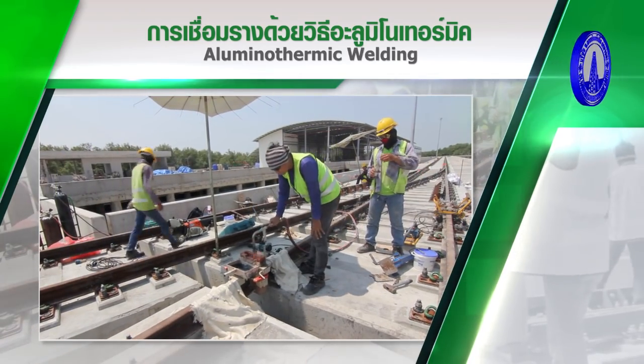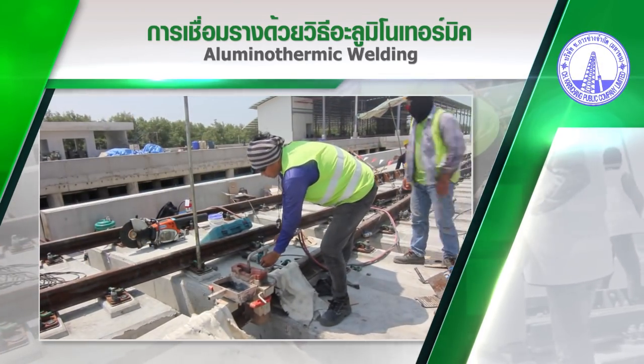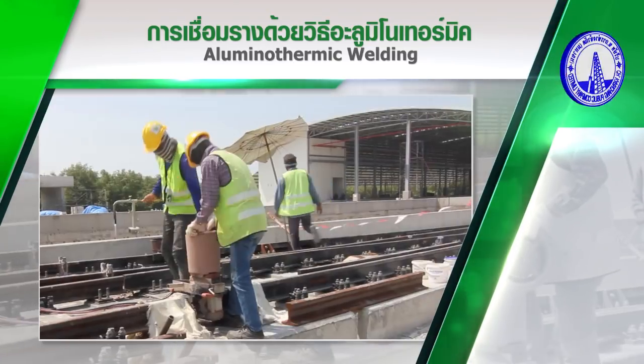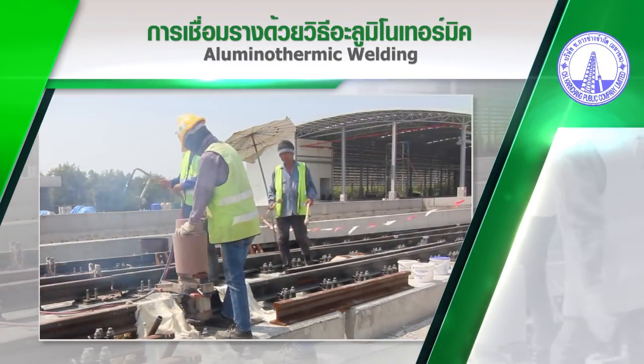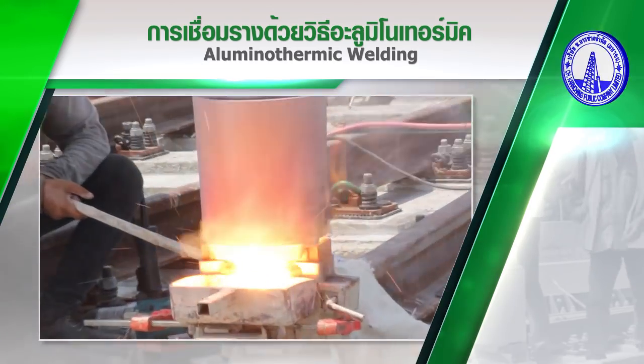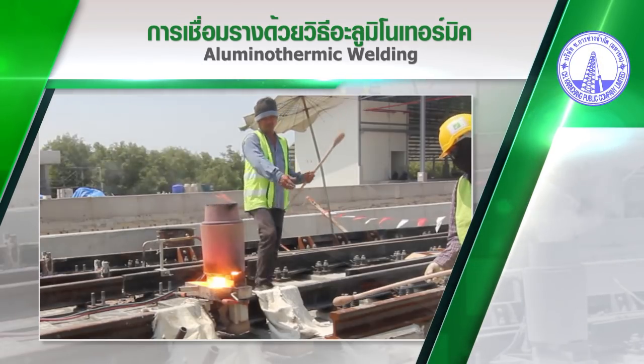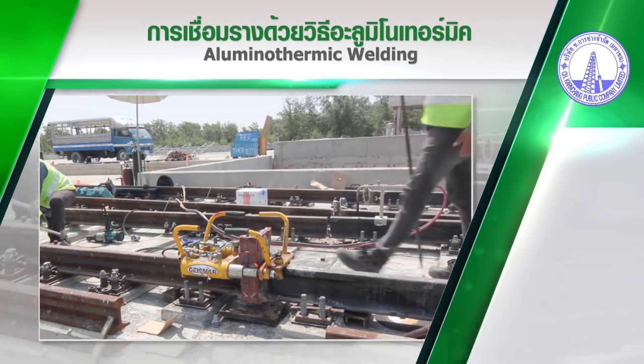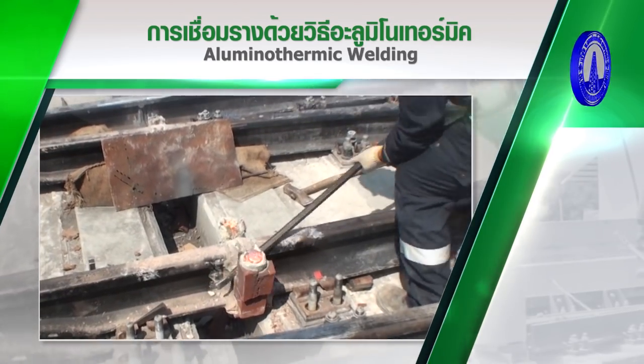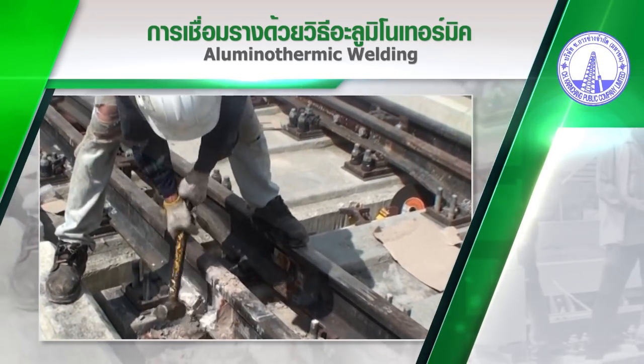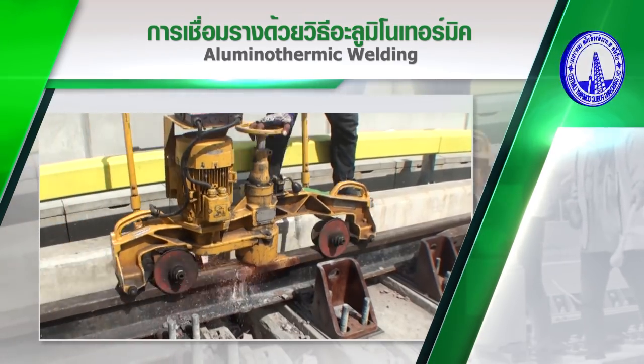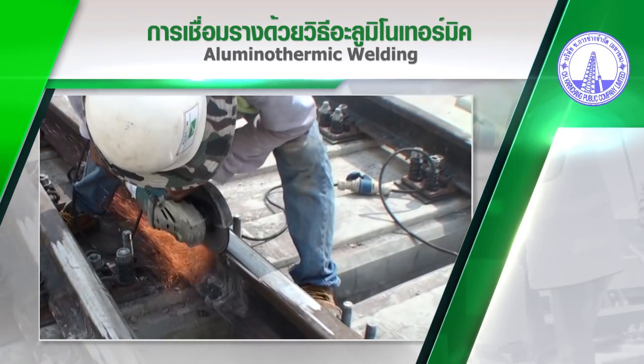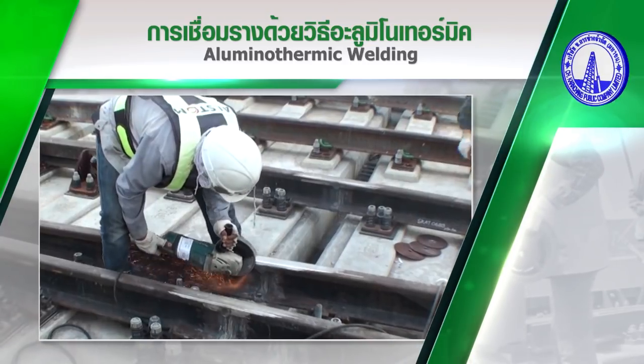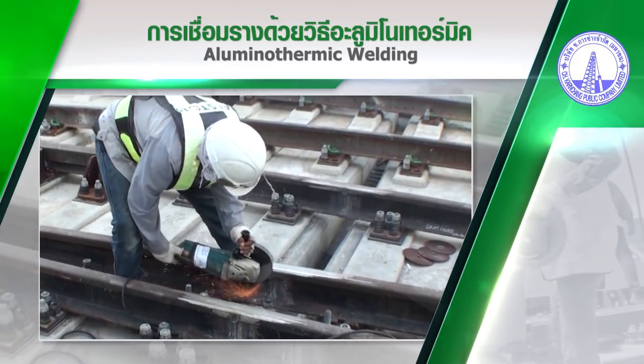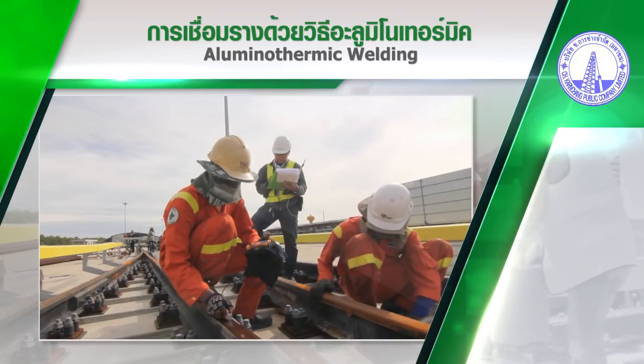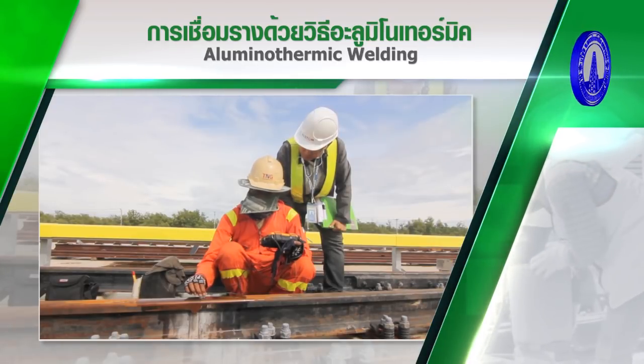preheating UIC 60 rails for 6 minutes, assembling the one-shot crucible type welding powder bucket, starting a fire to heat the crucible, waiting for a chemical reaction, shearing the welded joints with a rail shearing machine, grinding the rail head using the rail profile grinding machine, grinding the rail foot and web with the rail flexible grinding machine, and cleaning and inspecting the welded joints based on the aluminothermic welding method.